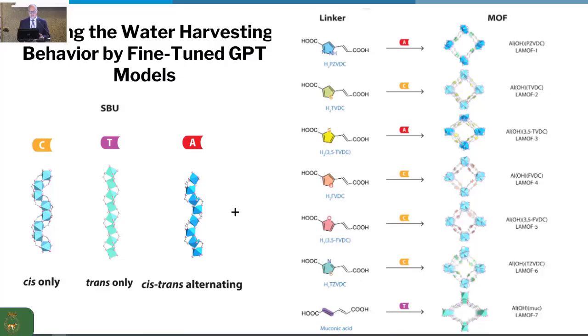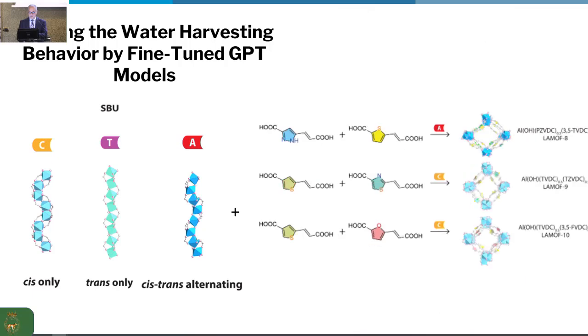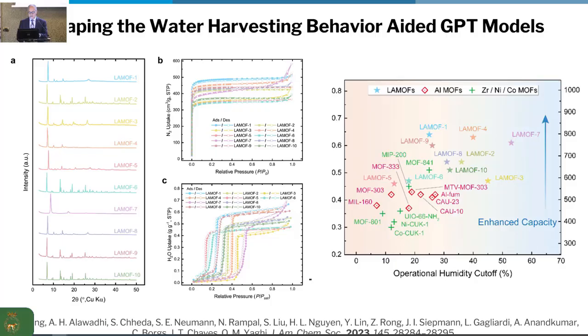Okay, so ChatGPT, we use it to fine-tune this. So we gave it some initial guesses, and it worked on generating different linkers of different composition and even mixed linkers. And we made the corresponding structures using robotics and tested them, and I won't describe everything on this slide, but it turns out that those MOFs from ChatGPT turned out to be the very, very best water harvesting materials. Okay, and that's because ChatGPT is not looking in a small spot. It's looking across the entire literature and taking that into account. And we as researchers don't have that capacity, especially not as fast as ChatGPT would be able to do it.